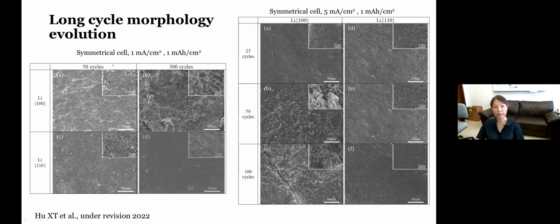And such accumulated defects actually start to appear if you look at the SEM of the surface at longer cycles. So this is a symmetrical cell processed at low current density, low capacity, at the end of 50 cycles to 300 cycles. And you see for the lithium 100, the surface gets very, very rough. But for the lithium 110, it's still quite flat. And similar results are obtained for symmetrical cells processed at higher current densities. For the lithium 110, you see always a very flat surface, but then these rough surfaces appeared.